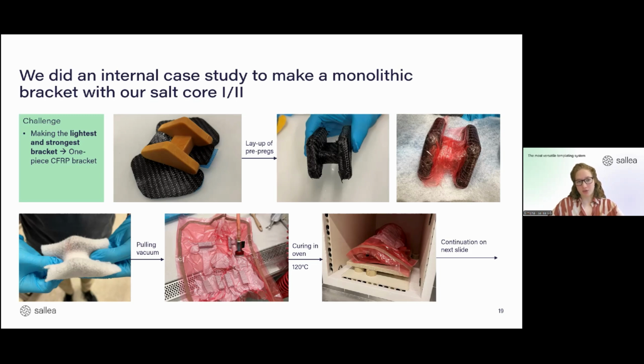And what we did is, so this salt core has been 3D printed that you see. Wait, I will turn on the laser. So here you see one of our 3D printed cores. Then we used the standard process to lay up the prepregs on top of our cores. And we did two layers of that before we wrapped it in the foil and prepared it for the vacuum bag. Pull the vacuum out of it, cure it in the oven at 120 degrees for a few hours to cure the epoxy.